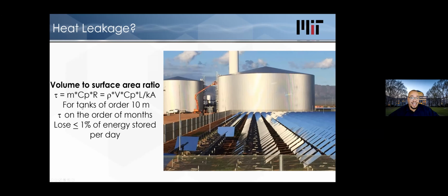So if you've got a tank, and this is an example of a molten salt tank for a concentrated solar power plant, there's tens of thousands of tons of liquid salt inside here. All right, so these are tanks on the order of 10 meters in diameter, on the order of 10 meters tall. On that order, you're talking about a time constant. The amount of time it takes for this to cool down is months. All right, so long that this thing effectively stays the same temperature over the course of just a couple of days. In those few days, you lose less than about 1% of the energy that you've got stored each day.